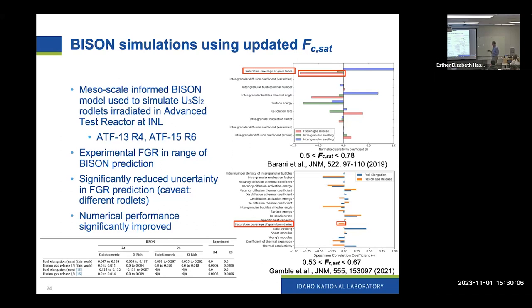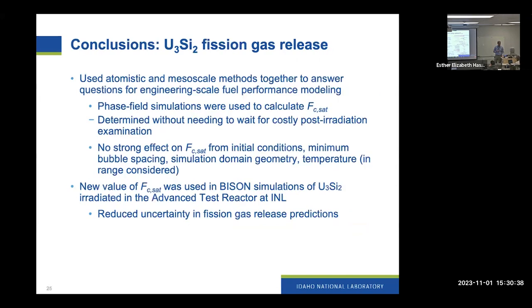And much to the happiness of our Bison colleagues, the numerical performance of the model was significantly improved as well, because some of these large saturation values led to very high swelling, with gas building up inside the fuel way more than is physical. That leads to a lot of swelling, a lot of contact with the cladding, and deformation of the cladding that wasn't physical. So by eliminating that range of parameters, we were able to improve the model performance quite a bit.